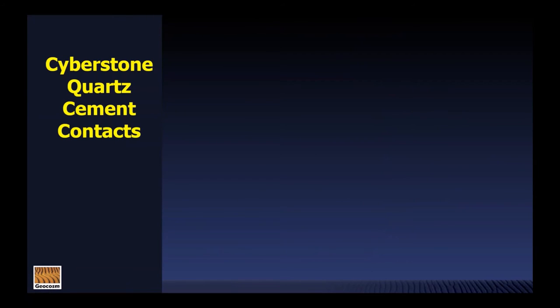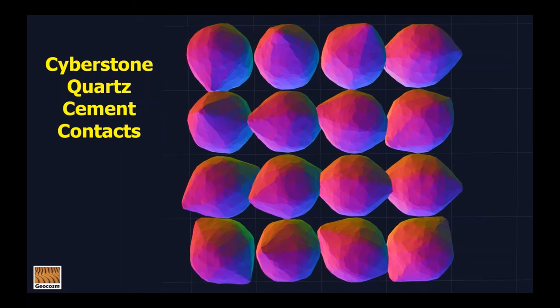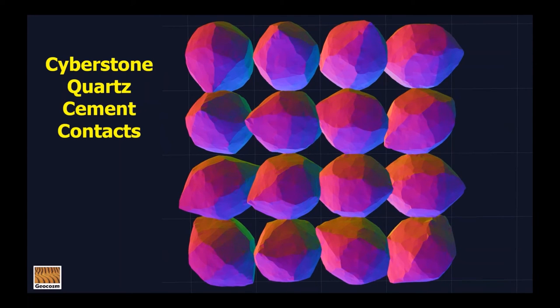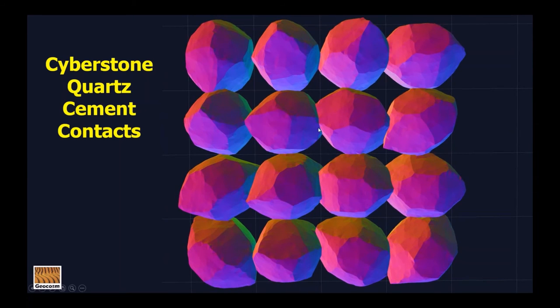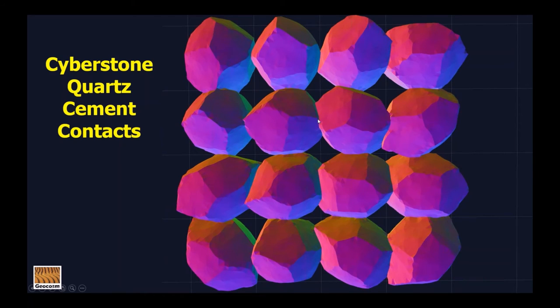So another thing that we are very concerned about in simulating quartz cement is that we accurately depict the area of contact that develops between the overgrowth and other solids, because this has a big impact again on the rock physics. And so to illustrate that, we start off with some spherical grains here, and you can see the boundaries that are beginning to develop between these grains. So we wanted to ensure that we are accurately depicting the area and geometry of these contacts because of the important effect that this has on the rock physics behavior as well as on the geomechanical behavior of the sandstone.